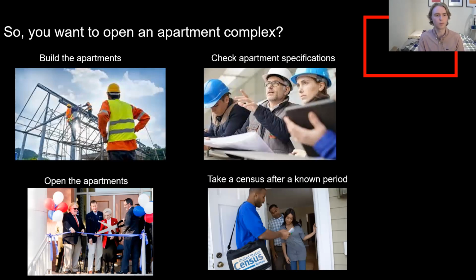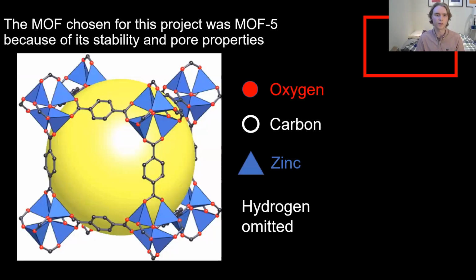So we can start with building our apartments, or in this case, synthesizing the framework. The framework that I chose for this project is called MOF5. And MOF5 has been around for quite a while. It was first synthesized in 1999, which is pretty early in comparison to the big MOF boom that has been happening more recently. And the reason I chose MOF5 is, one, because it's quite well documented, and its synthesis is not particularly complex. I also chose this framework because it has very good stability in a number of different solvents. And that would be important provided I could make it to a phase where I want to be looking at different solvent effects inside of a framework.